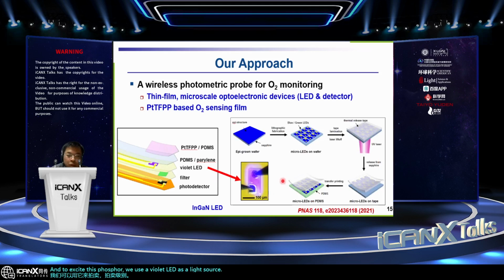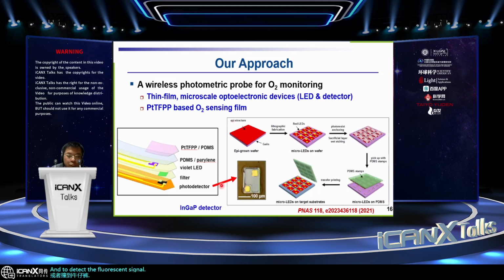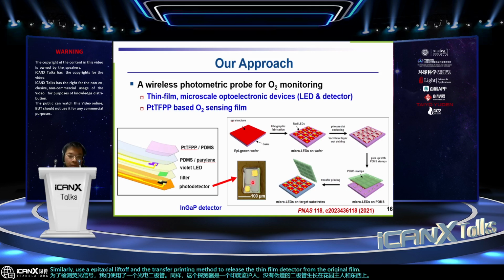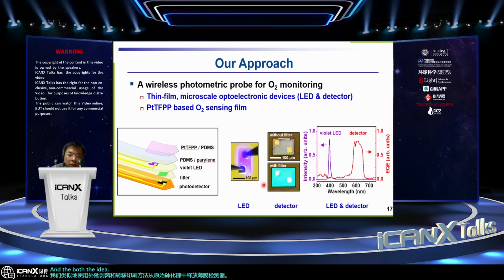This LED structure is an indium gallium nitride diode grown on a sapphire substrate, and we use the epitaxial liftoff and transfer printing technology we developed to release this thin film LED from the original rigid substrate for heterogeneous integration. And to detect the fluorescent signal, we use a photodiode. Similarly, this detector is an indium gallium phosphide diode grown on gallium arsenide substrates. We similarly use epitaxial liftoff and the transfer printing method to release the thin film detector from the original gallium arsenide. Both the LED and detector have a geometry of about 100 to 200 micrometers, and a thickness of only a few micrometers after the liftoff.